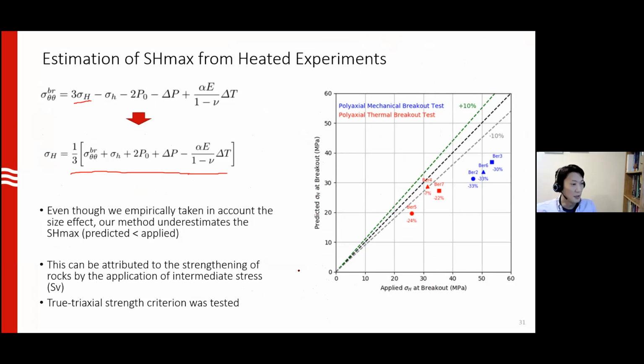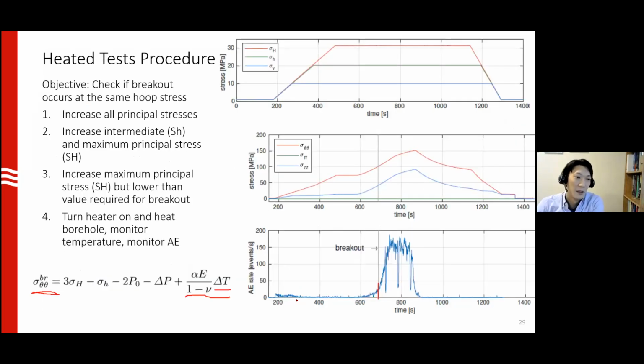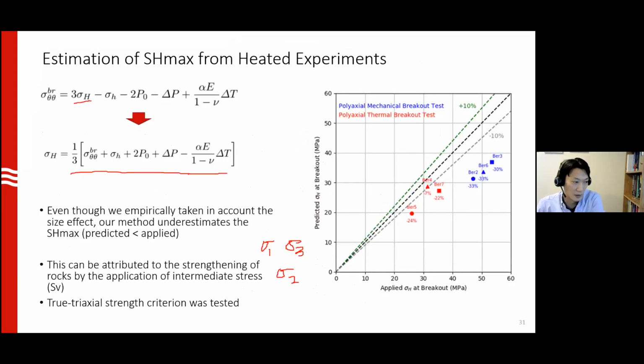So we attribute that to the strengthening of the rock due to the intermediate stress. The Mohr-Coulomb criterion only looks at sigma 1 and sigma 3, but it's been very well known for decades that the intermediate stress sigma 2 also has an influence on the rock strength. Indeed, if you look at the middle figure again, especially when you heat, it's not only the hoop stress that is increasing, but you're also increasing the intermediate stress quite a bit. So we think that's the cause of why the borehole appears to be stronger, and therefore we need to modify our approach and use a true triaxial strength criterion.